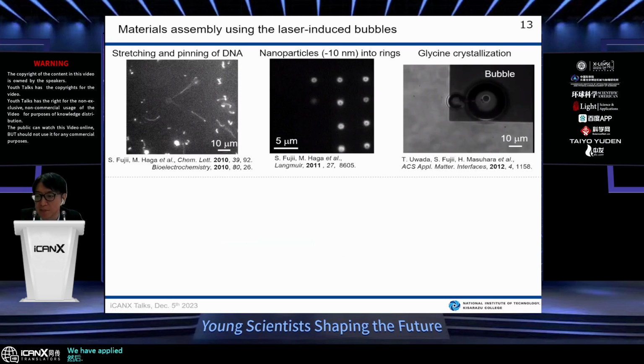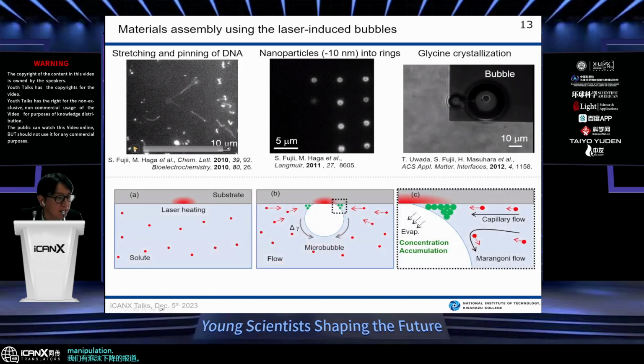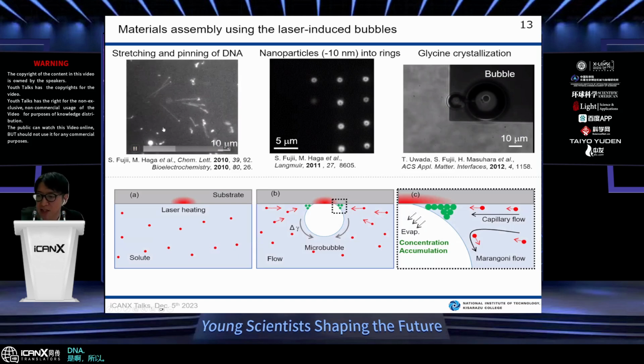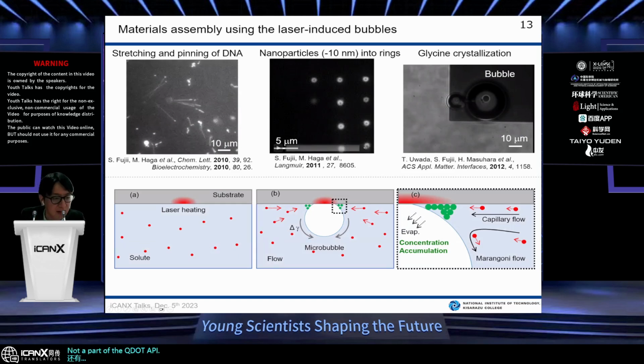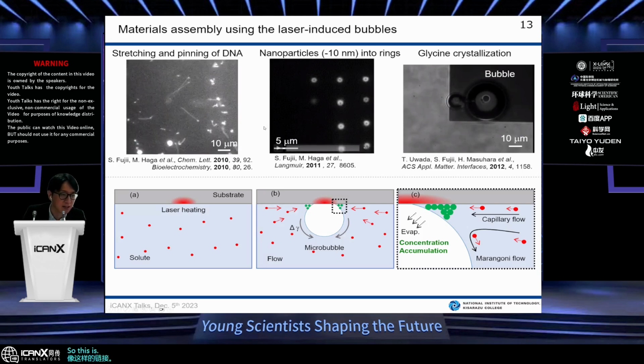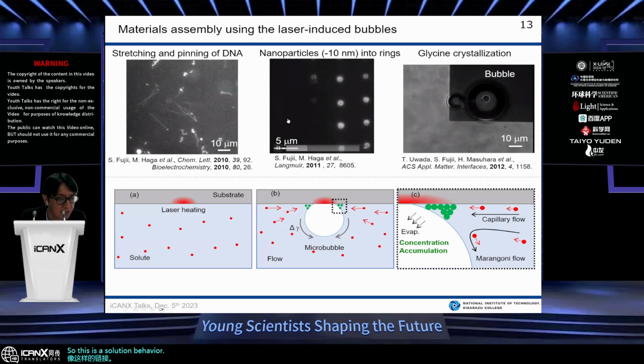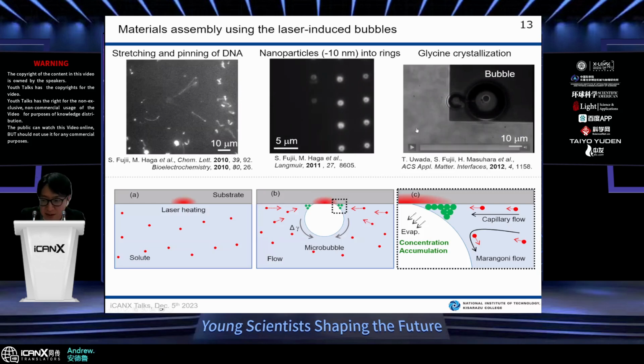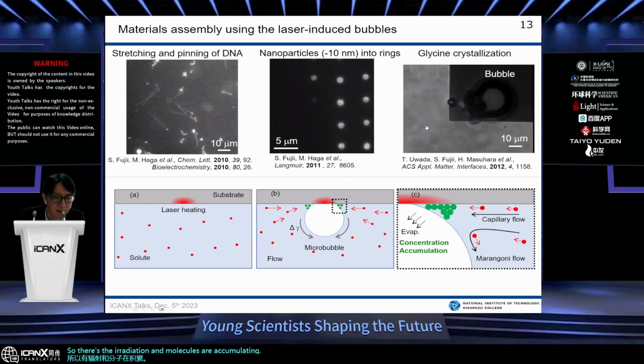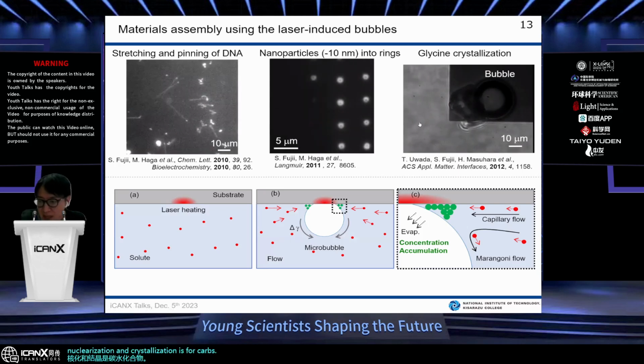And then we have applied the bubble property for materials assembly. We have reported the bubble for manipulation of DNA, stretching and pinning, and nanoparticles, quantum dots, into a ring like this one. So this is the solution behavior. When laser irradiation is on, quantum dots form a ring shape. And the next result is crystallization of glycine molecules like this one. With laser irradiation the molecules accumulate, and then nucleation and crystallization occur.